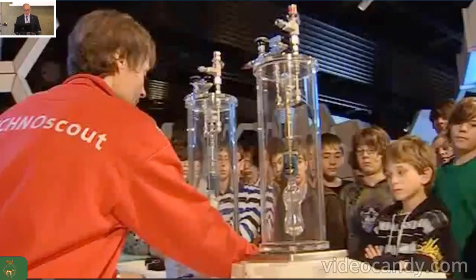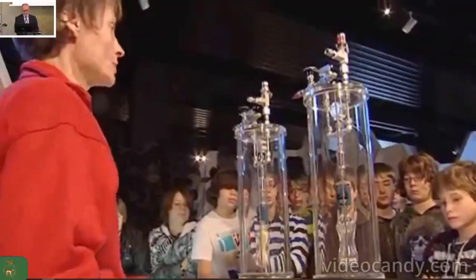And this is a demonstration. This requires audio. In this demonstration, we'll show how an empty canister versus a canister that has a MOF, and the canister that has a MOF holds more gas than the canister without the MOF under the same temperature and pressure. Okay? Let me repeat. The empty canister versus the canister with the MOF. The canister with the MOF holds at least 3 times more gas than the one that does not have the MOF, because the MOF has those microscopic pores that compress the gas and allows the interior of each granule to be much larger than the exterior. And so this experiment provides a striking demonstration of MOF storage capacity.